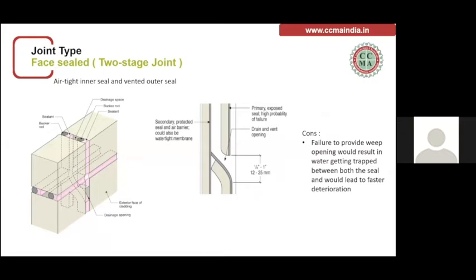The important thing one needs to note in this type of sealing is that there should be a weep opening in the outer seal. This would allow the pressure between the seals to be equivalent to the outside pressure. Drawback of this method: failure to provide a weep opening would result in water getting trapped between both the seals, and it will lead to faster deterioration.